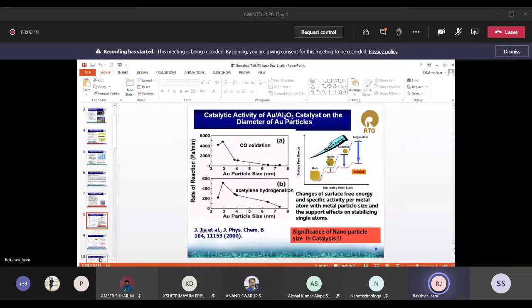And though we are in the nano domain, when I say gold at 7 nanometer or 8 nanometer, then also I'm using a nanoparticle. But if you see this graph, it is not very active. So it is only showing very large activity when it is around 3 nanometer or less than 4 nanometer. You can see here the activity of this gold is very high when it is in this domain.